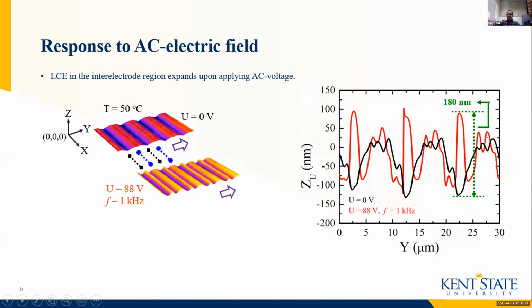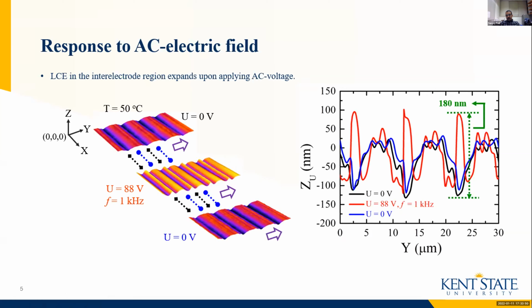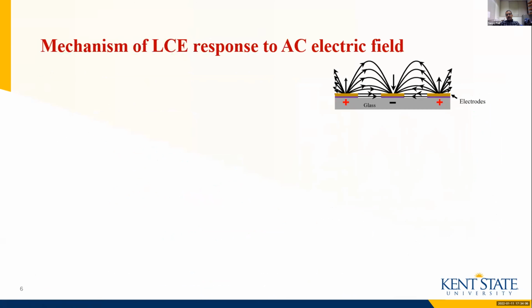Now, if we apply AC voltage at 1 kilohertz frequency and magnitude of voltage 88 volt, we see from the surface profile as well as from the line profile that the topography height in the inter-electrode region increases. We saw about 180 nanometer of height change. We take the electric field off, it restores itself. The actuation of liquid crystal elastomer by AC electric field is a strong function of field magnitude U, frequency F, and temperature.